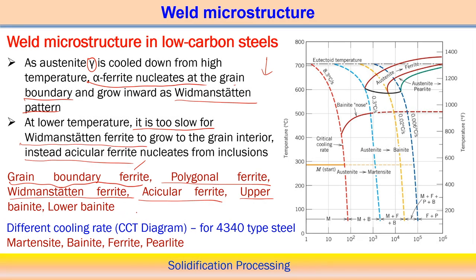Just as an example, we will be able to understand how the cooling rate affects the different structures. It is a very simple example, and I hope it is very common in an engineering materials course also. If we follow the CCT diagram of 4340 type alloy steel, a very standard graph, the CCT, continuous cooling transformation diagram, for one particular 4340 type of steel, we can see when the transformation starts at this particular point, and this red dotted line indicates one constant cooling rate here.